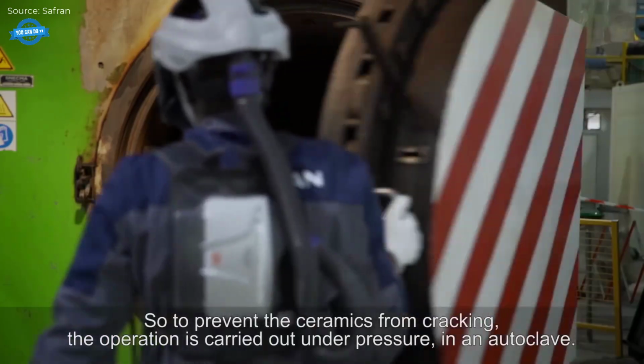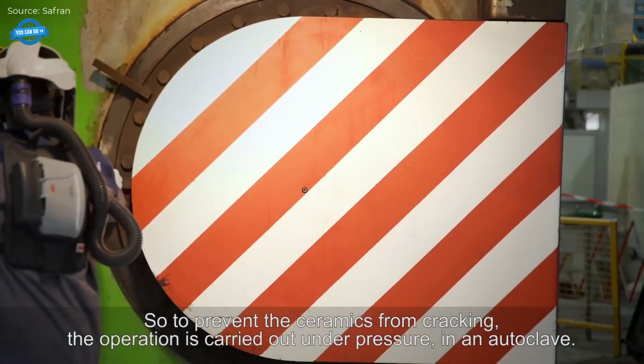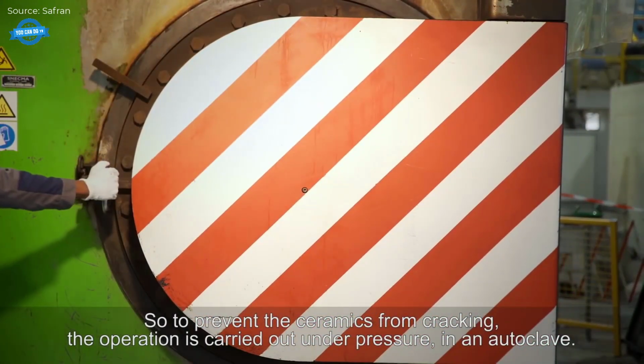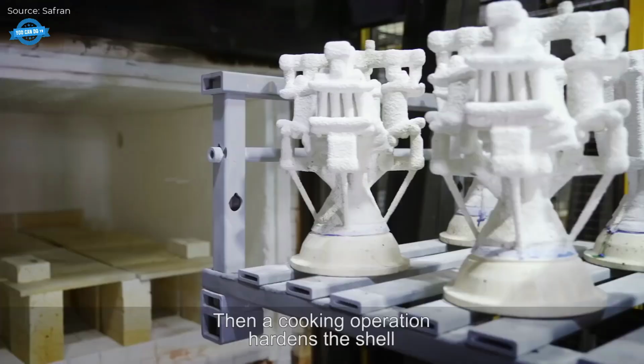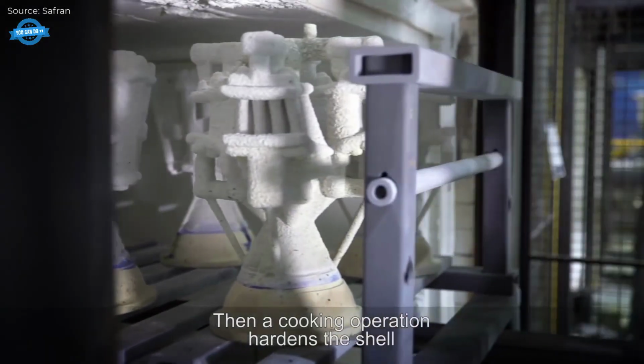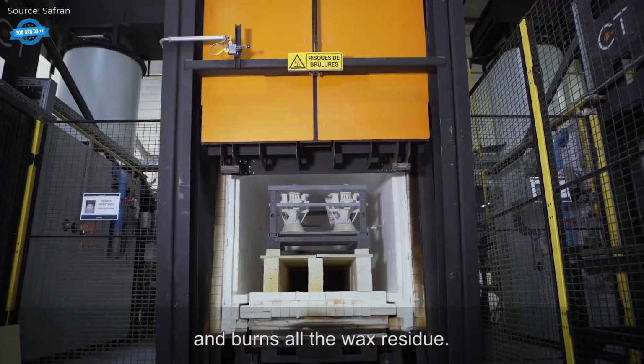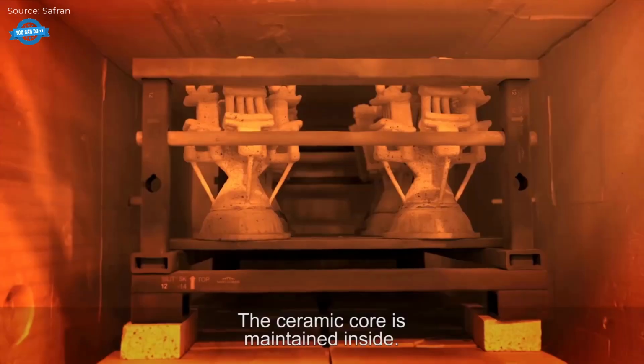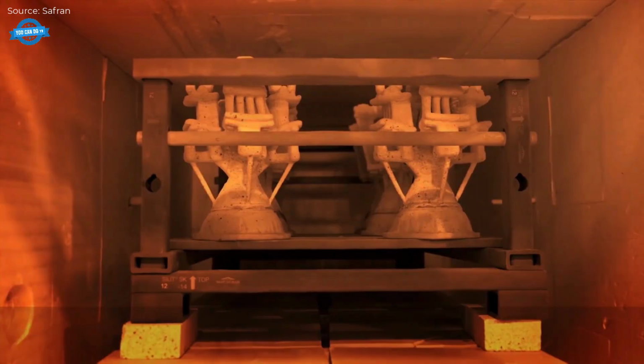Once the shell is complete, the wax inside is carefully removed through a process called dewaxing. This step takes place in an autoclave, where heat and pressure are applied to melt the wax out without cracking the delicate ceramic shell. Finally, the shell is baked to harden, preparing it for metal casting.